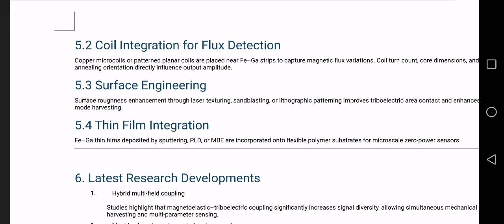Coil integration. Copper coils capture magnetic flux change. Performance depends upon number of turns, core geometry, and annealing orientation. Surface engineering. Surface roughness is improved by laser texturing, sandblasting, and lithography. This increases contact area and enhances triboelectric output.